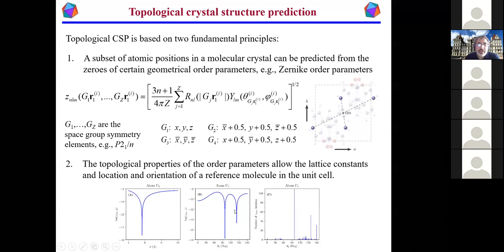And in fact, if you do a histogram over lots of n, l, and m values, so you go up to very high n, l, and m, right? You do a histogram, you see that, let's say, along the theta direction, I have multiple minima, one really stands out, right? And so by doing these histograms, we can find these highly preferred locations appearing as high population minima in this histogram. And these become a way to use geometry to predict where these atomic positions are actually going to lie in your unit cell.